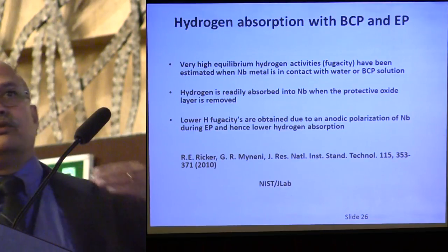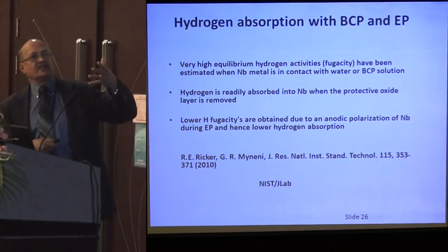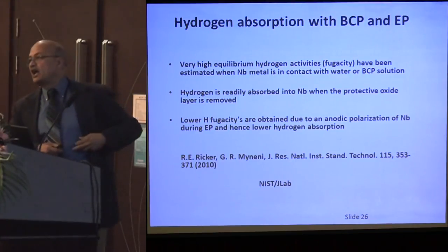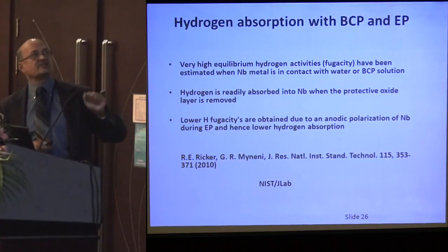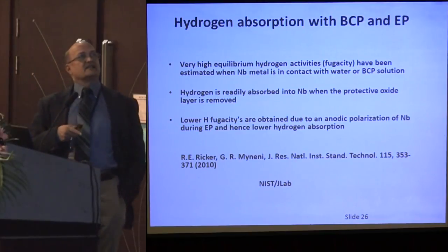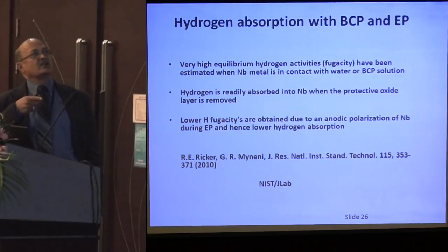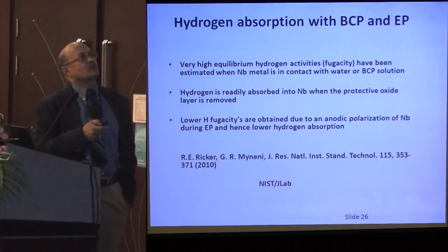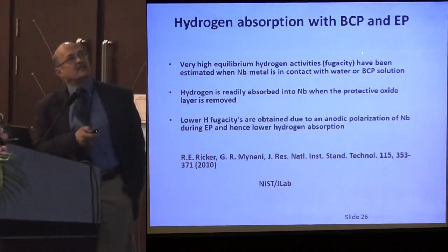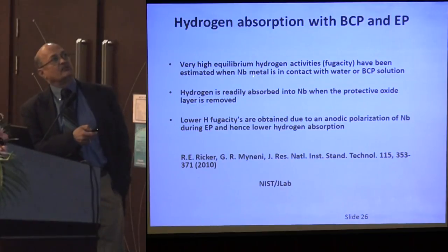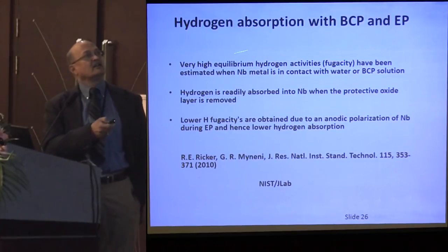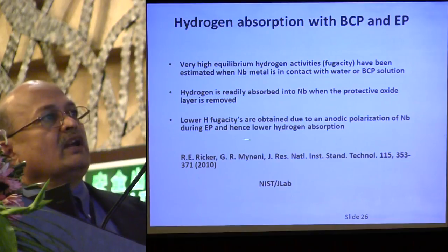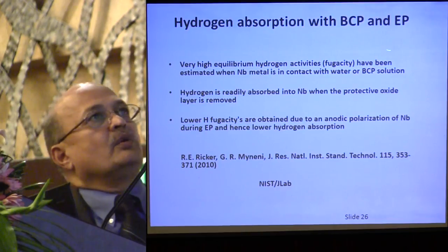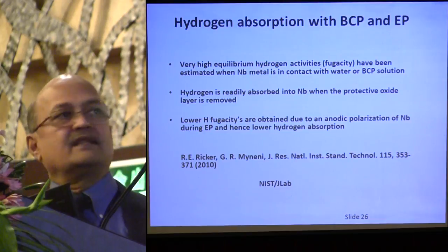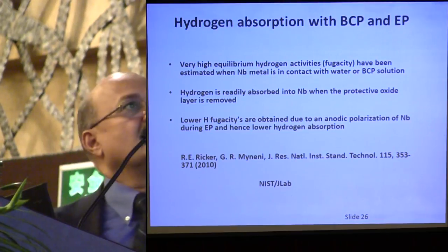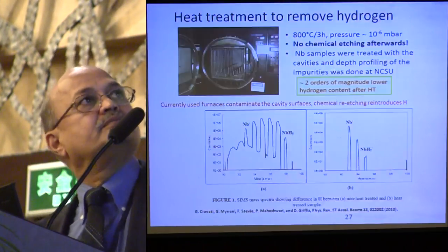What happens is, as soon as you do the process cleaning, within a few seconds a niobium pentoxide forms on the cavity surfaces, and that actually minimizes the introduction of hydrogen into niobium. But during these processes, we basically remove the pentoxide. As a result, water comes in contact with niobium, and hydrogen goes in. The lower fugacity of hydrogen in electropolishing actually minimizes the absorption of hydrogen. This is the main difference between these two processes.